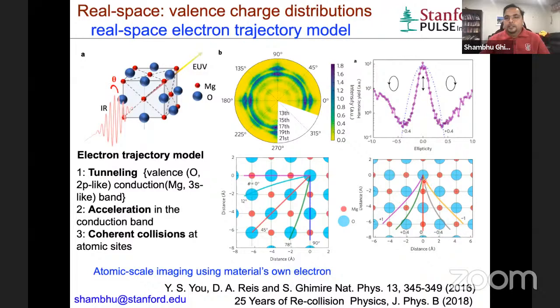In this case, for example, this trajectory is completely missing the nearest neighbor atomic sites, and that corresponds to the minima. So basically, since this is a single crystal solid and we can change polarization, rotate the crystal and do these nice things, we can probe the charge distribution in the crystals. This is also important and could be complementary to X-ray methods, because as we know, the optical methods are more sensitive to the valence charge density, which is what you care about, right, in terms of understanding the chemistry of the system.